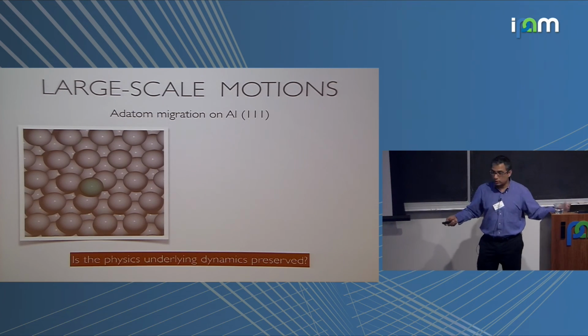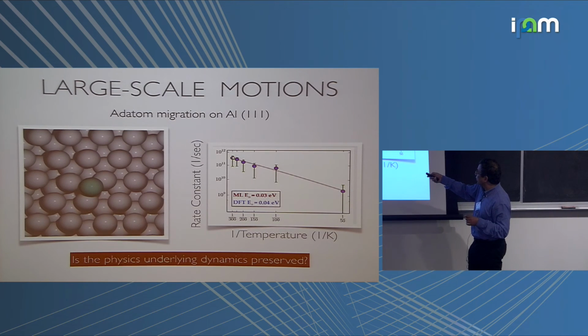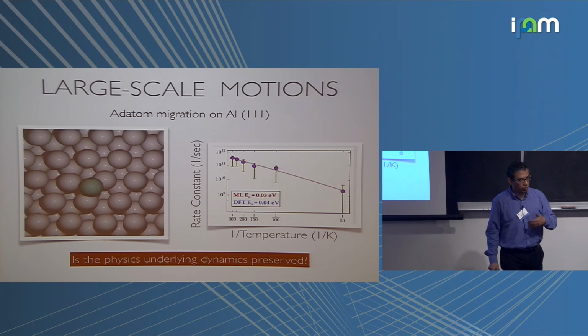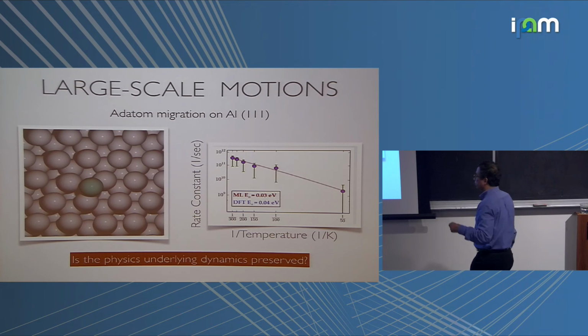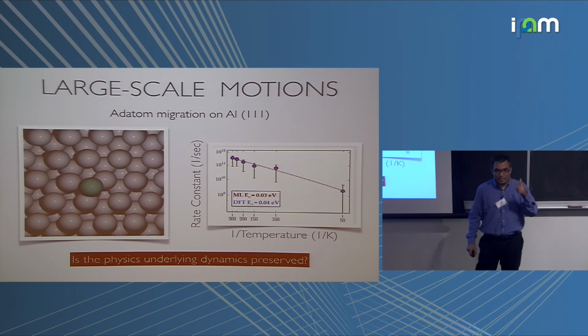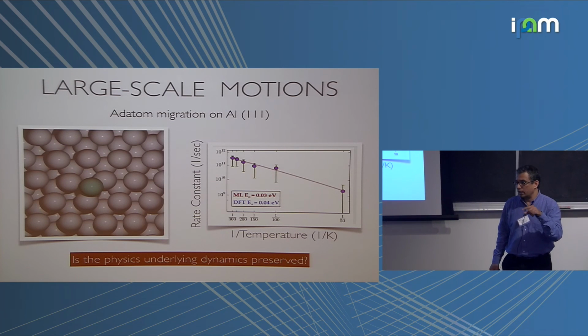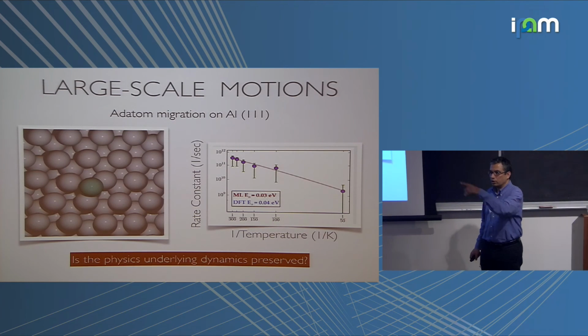For this particular case, this is the reciprocal temperature versus the rate constant of the average hop, and these points are the results of the simulation, and that's a fit. From the slope we get the activation barrier according to the machine learning force field, and we separately calculate the activation barrier using zero temperature DFT, nudged elastic band calculation, and that's what we get. We have done the same thing for vacancy diffusion in bulk as well, and we get the same sort of trend. Yes, question?